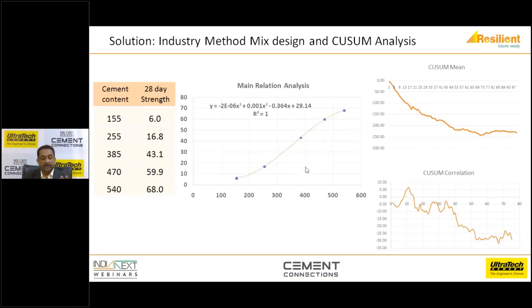For example, at a 400 cement content, you know that this concrete should be giving you 47 newtons. So at every cement content, you know what is the equivalent strength this particular group of materials will give you with that particular cement. This is used as a baseline for monitoring the performance of concrete at site. So when you get your cube results, the cube result is first compared against the base strength, what it's supposed to give, and the sum of the deviation is monitored.